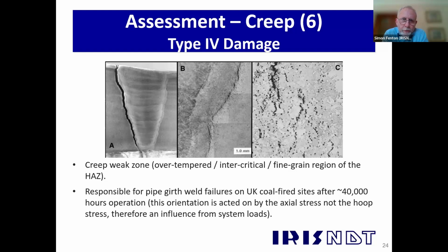Not only is it called Type 4 damage, we also call that region the creep weak zone, the over-tempered region, the intercritical region, fine-grained region. So it's got lots of different names. But it's the same thing. It's a creep weak region of the weld. In that previous bend failure that I showed you, similar systems had suffered weld failures after 40,000 hours. And this was a combination of the creep weak zone, but also problems with things like the pipework supports leading to high system loads. So high system stresses acting on that Type 4 region.